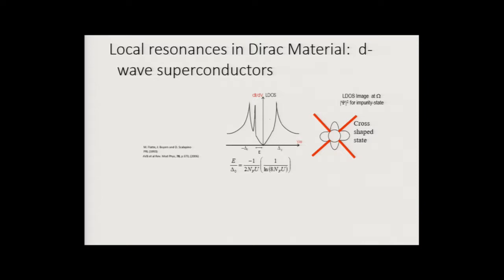Nothing surprising, okay? Now, what we were looking at was a slightly different aspect of it, namely the alignment of the impurity resonance. This resonance has energy, but it also has a real space shape, and will be aligned with the nodes of the gap, and therefore you can make a guess about the nodal structure of the gap, because the gap works as a retention wall. If I have, for instance, water, and I drill four holes along these kinds of directions, the water would leak out. So this impurity resonance will have a cross-shaped form.